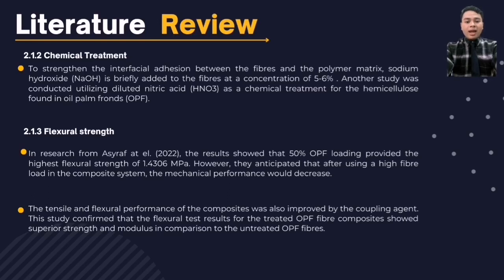For the flexural strength in research by Asyraf et al. (2022), the results show that 50% OPF loading provided the highest flexural strength of 1.4306 MPa. However, they anticipated that after using a high fiber load in the composite system, the mechanical performance will decrease. As revealed by the morphological study in the experiment, fiber pull-out was the cause of this decrease. It happened because the composite strength was reduced by insufficient wetting between the fibers and matrix.